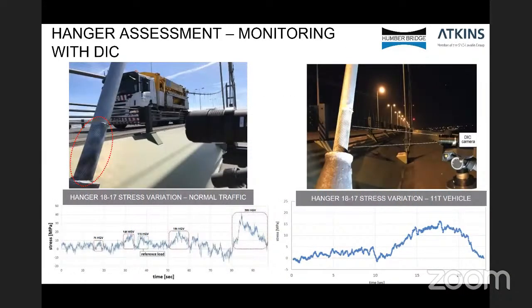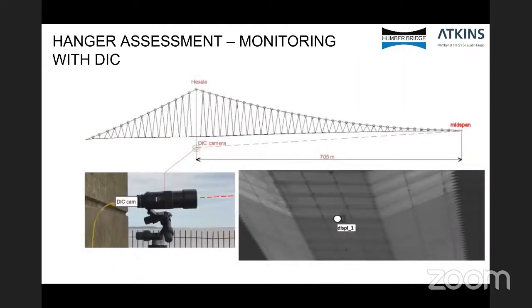This was in situ strain monitoring that we carried out for the bridge. This is using a digital image correlation system where we use very high resolution images of the surface to determine strains in real life. And this was correlated against our model and found to show good agreement, which enables us to understand the loading throughout the cable. We go to the next slide, which shows the DIC monitoring used not only for the micro strains of the cables on the hangers, but also for the overall movement of the bridge deck, which we found was also in agreement.